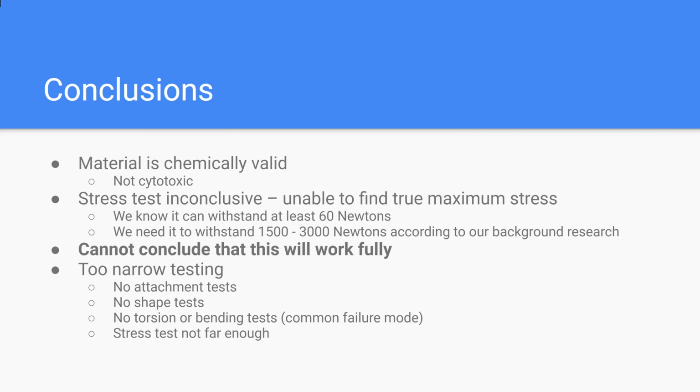Here are our conclusions. Our material is chemically valid and not cytotoxic according to our cytotoxicity test. Our stress test was inconclusive and we were unable to find the true maximum stress. We know that it can withstand at least 60 newtons, but we need it to be able to withstand 1,500 to 3,000 newtons according to our background research. Because of the inconclusive stress test, we cannot conclude that the NinjaFlex material will work fully.